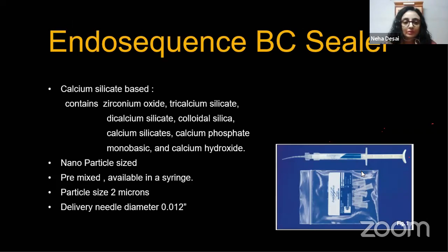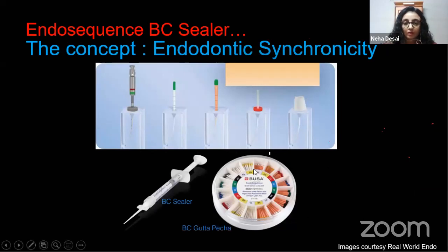Talking a bit more about Endosequence BC sealer, it is calcium silicate based. It contains zirconium oxide, tricalcium silicate, dicalcium silicate, colloidal silica, calcium silicates, calcium phosphate, monobasic, and calcium hydroxide. It has got nano-sized particles in it. It is pre-mixed, available in a syringe. The particle size is just 2 microns, and the delivery needle diameter is 0.012 inches only. That is a very, very small opening through which the paste has to be really pushed into the canal. Hence, it causes a lot of hydraulic pressure, and this helps in achieving the hydraulic single cone Gutta-percha obturation technique.